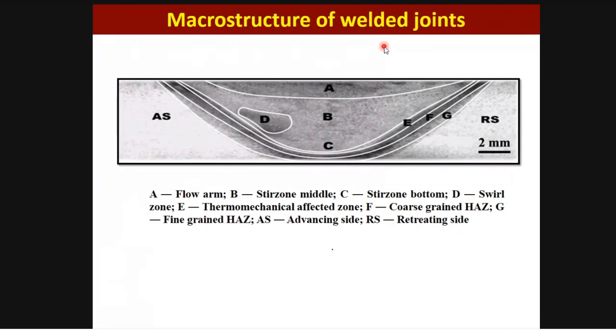So after welding the cross section, we observed a lot of different regions with different microstructure, and you will find nearly 5 different regions itself. So A is the top region, the flow arm, this region is called, and that's the shoulder influence region. And B is the middle region, a stir zone middle region, and C is the bottom stir zone region. And below that, there is a swirl zone here, on the side, and then it is a thermomechanically affected zone. And then in the steel, definitely you have coarse grain and fine grain heat affected zone. And again, there is asymmetry of advancing side and retreating side.